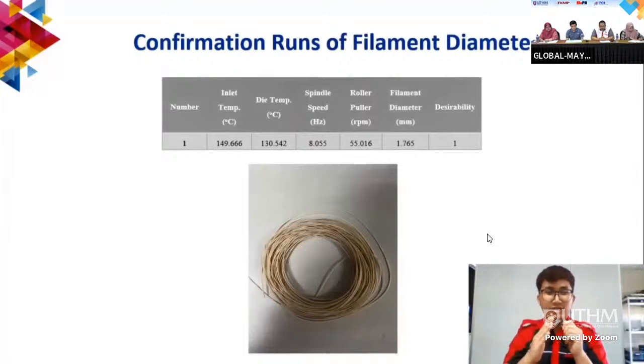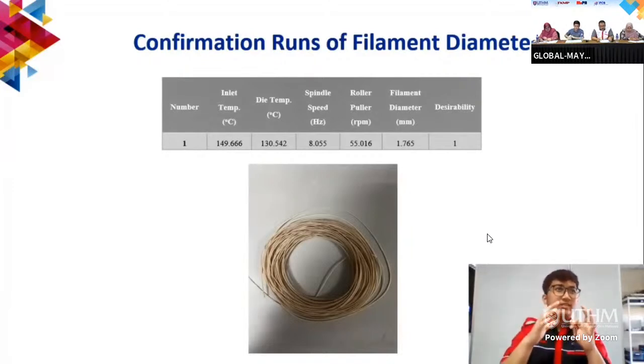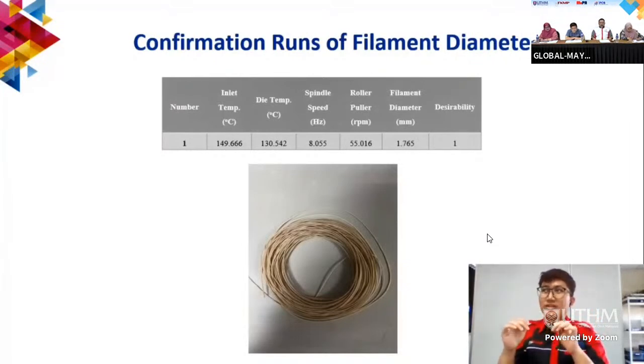The inlet temperature is around 149.666, the die temperature is 130, the spindle speed is around 8, and the roller puller is 55. And then we get the same output with plus or minus 0.01 millimeter. So from that, we know that this study was successful because we can get the parameters within the range of 1.75 to 1.8 millimeters.